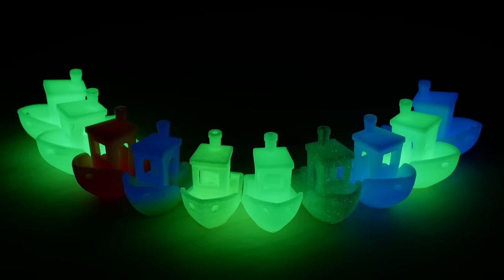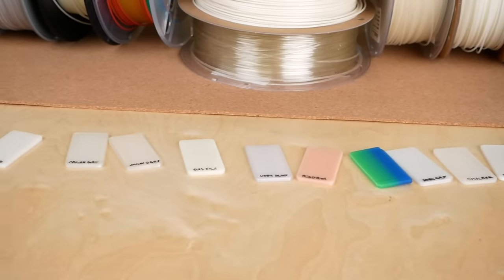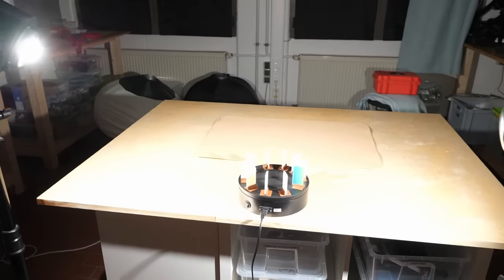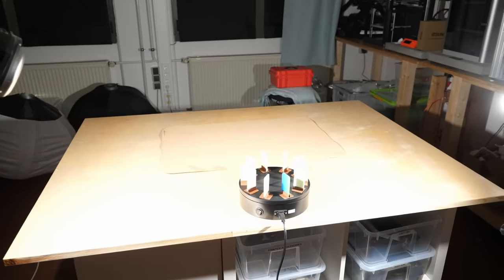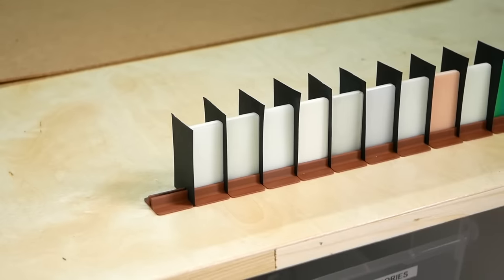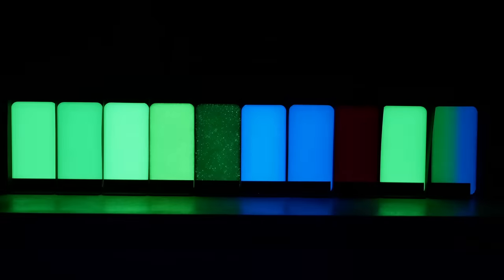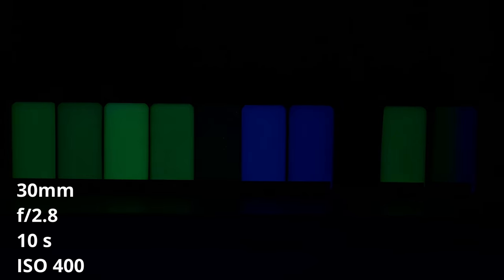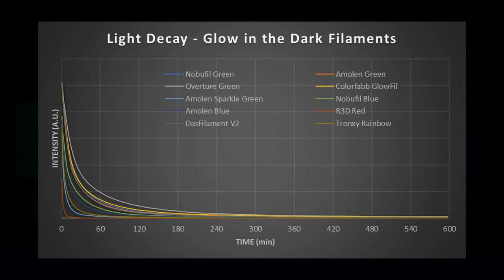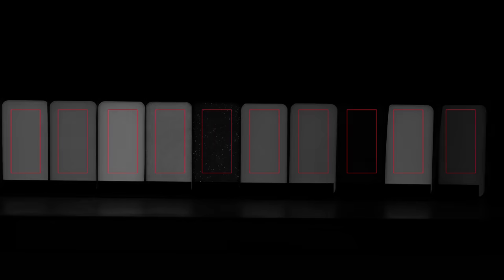To find out how bright the materials are and how long the light lasts, I tried to approach this at least a bit scientifically. I printed 3mm thick test swatches with 100% infill from each filament, then charged them as evenly as possible using an electric turntable while blasting them with two 200W 5500K studio lights. UV light would have been even better, but in a real-life scenario you typically charge these parts up with regular indoor light. I placed them next to each other separated by cardboard so one doesn't shine onto the other, then took images in 1-minute intervals with all manual camera settings. After 600 images and 10 hours, I used a Python script to analyze the images, converting them to grayscale and calculating the average gray value over each marked area to extract brightness over time.